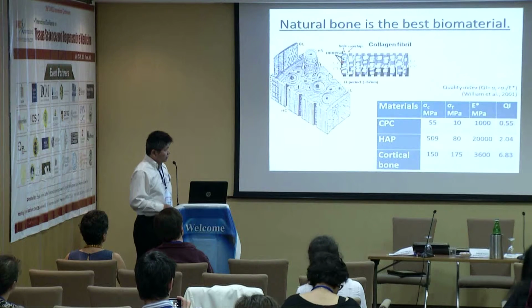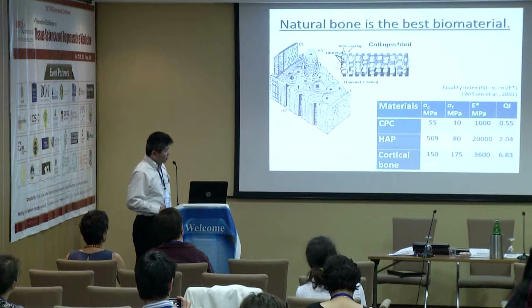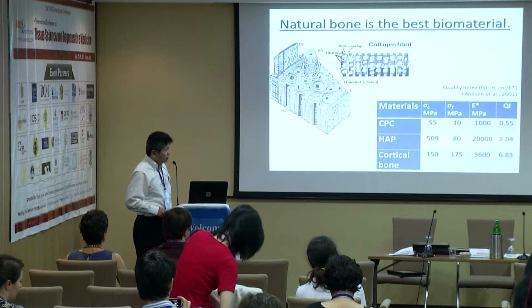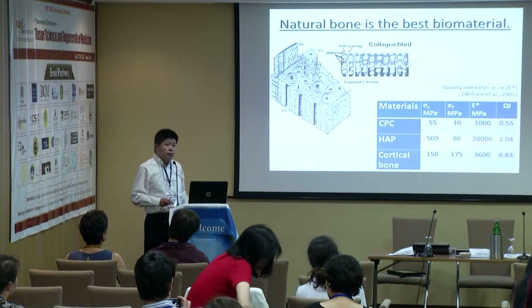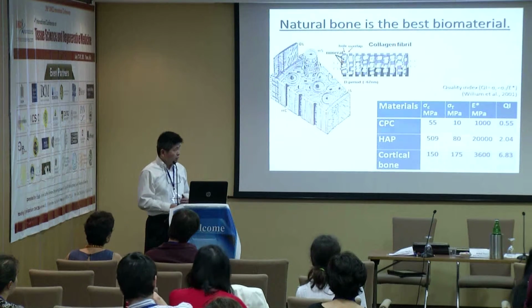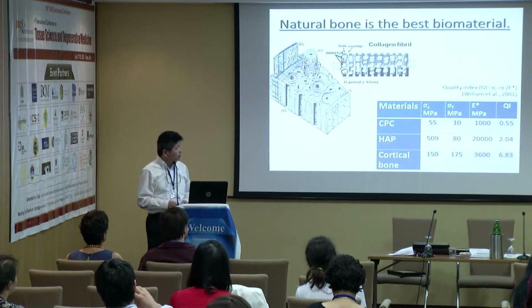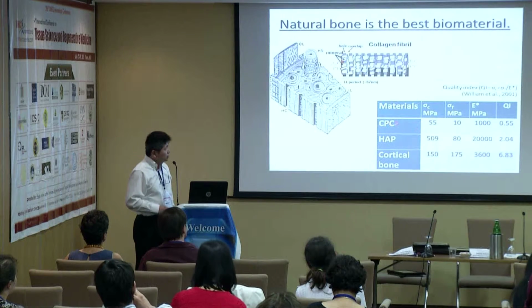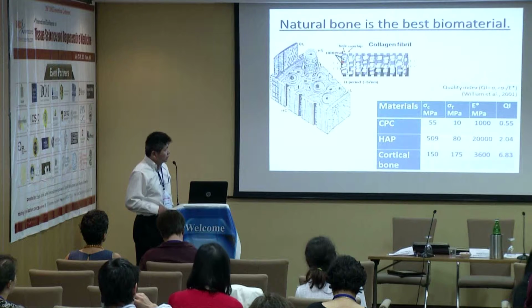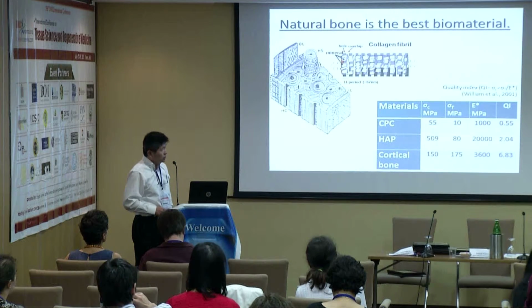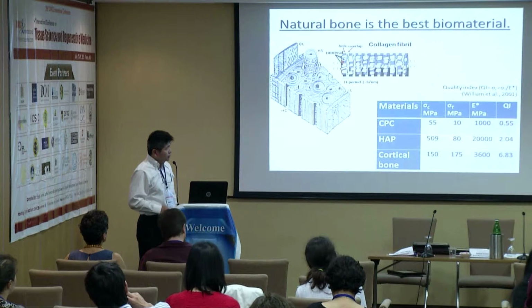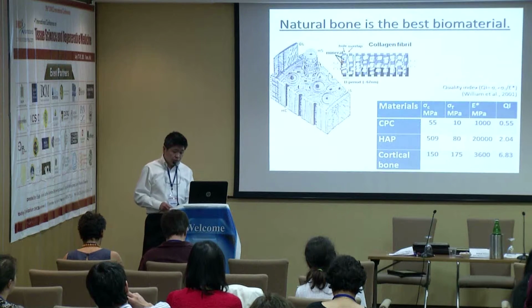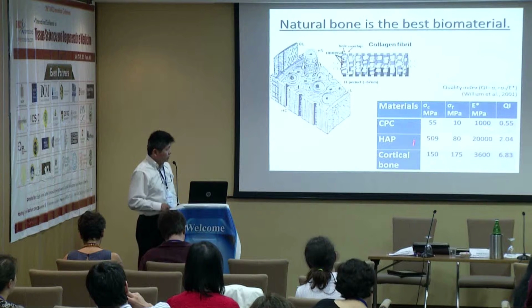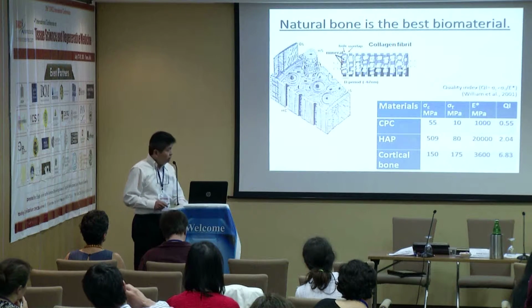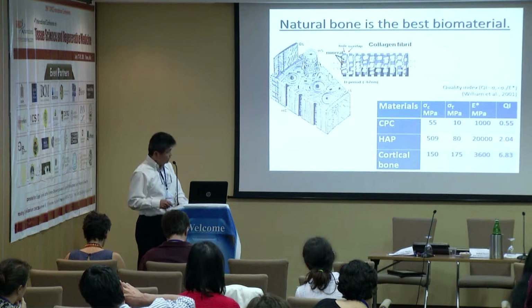For example, from the early Williams formula, they calculate a quality index for cortical bone by multiplying the compressive strength by the tensile strength and dividing by the stiffness. Then you get a quality index like 6.83. So the artificial material we would like to reach is something around that number to support the defect. However, most of the materials currently used, especially inorganic materials such as calcium phosphate cement, have a QI of only 0.5, and hydroxyapatite, because of its brittle nature, has a QI of only 2.0. So we do need to find some new material which can take over both the organic and inorganic benefits, and make a strong artificial material.